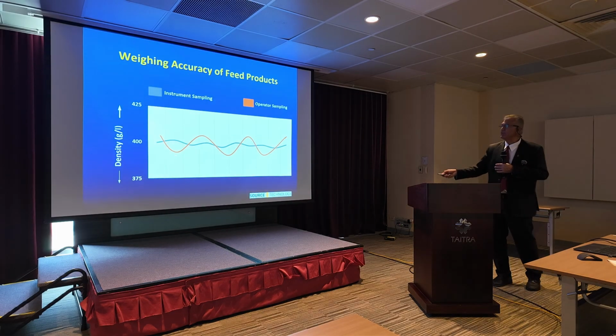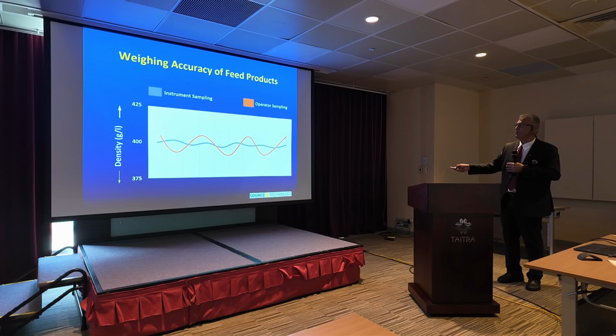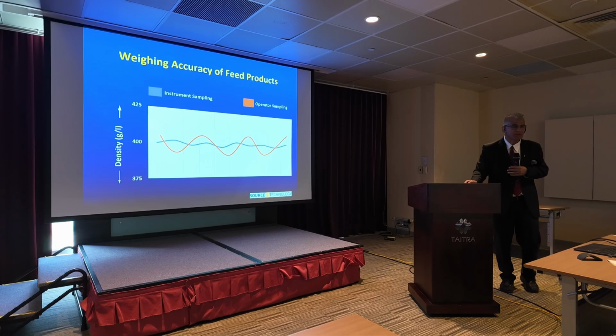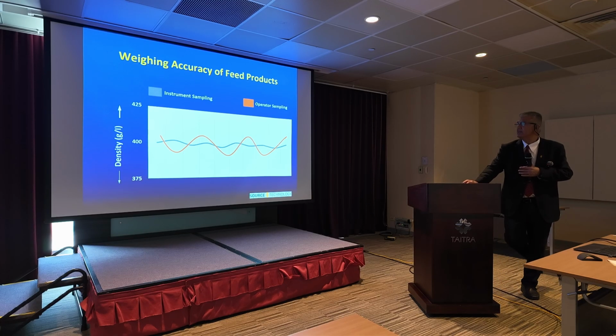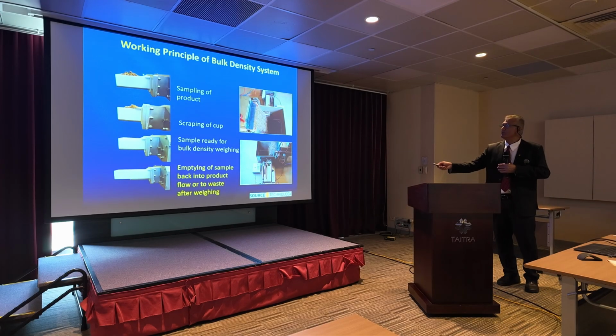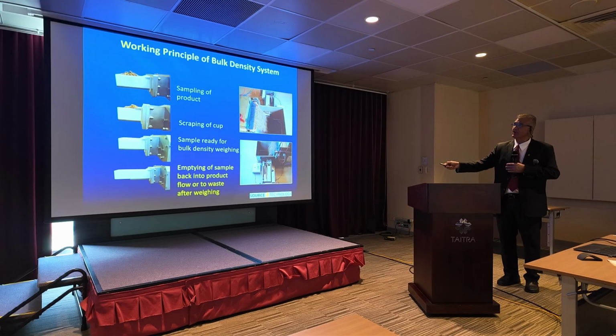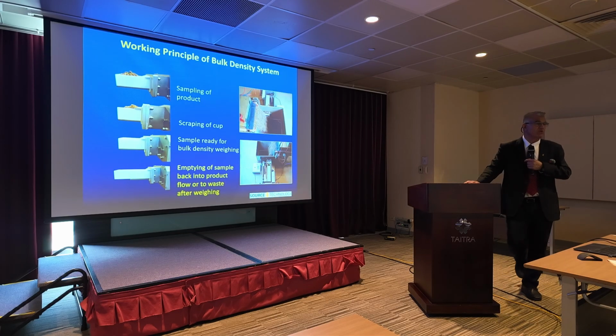Therefore, if you have it, you can see here the variation. This is the operator sampling, and this was the instrument sampling. And you get maybe less than 1% variation when you do that. How it works is that the unit comes outside, takes the sample, scrapes the sample, the machine does it, and then the sample is ready for the density, and then it empties it. Therefore, you can put it going into the dryers, going into the extruder, you can measure density online anywhere you want, which is very important especially for making floating and sinking feed.